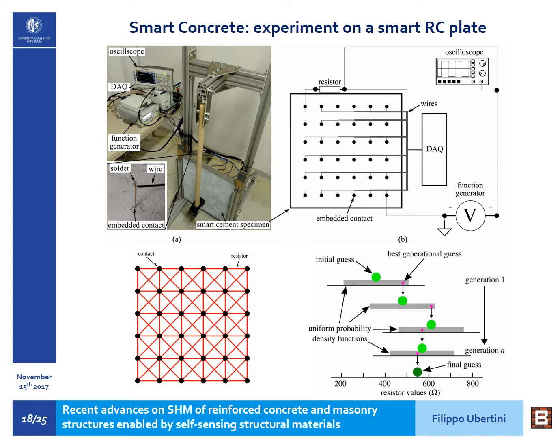The example consists of a smart concrete plate, again made of cement paste doped with multi-wall carbon nanotubes. We have put this plate on a device that allows us to apply hammer hits with controlled energy to reproduce a certain number of hits, all of them having more or less the same energy. On the plate we have several contacts embedded, as we see on the top right of the slide. We apply a voltage input through a square wave across two electrodes, and we measure voltage drops across all remaining pairs of electrodes.